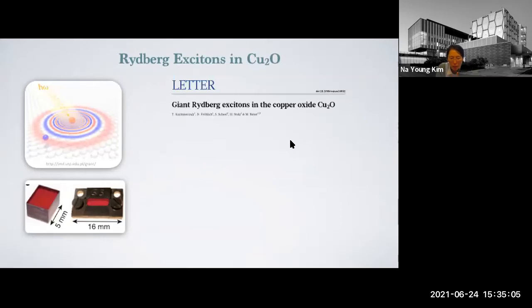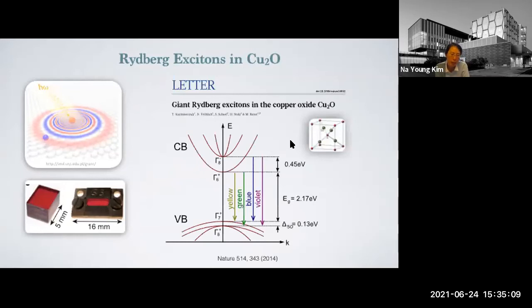It showed this giant Rydberg exciton. What is it? I'm just showing a quick band structure. It is a semiconductor, and cuprous oxide is a historic material, the first semiconductor in which excitons were observed. It is also actively used to make solar cells, so it's a quite long-standing semiconductor. As a simple cubic crystal structure, its band structure is extremely interesting. Can you imagine that this red-colored crystal can emit 4 different colors, like yellow, green, blue, and violet, depending on which optical transitions between the 3 valence bands, if I include the degeneracy, and the conduction bands. In this particular talk, I'm going to talk about the yellow, which is the lowest energy transition.